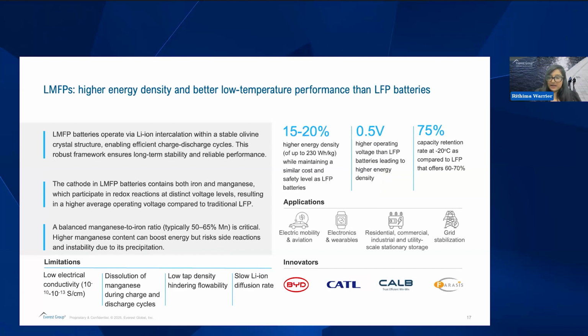Now, moving on to LMFP batteries. LMFP batteries are nothing but an upgrade of LFP batteries, and let me explain how. It's just that one letter M, which is manganese. So it is lithium manganese iron phosphate, which means that instead of entirely iron, it is able to incorporate manganese as well. And what this addition of manganese does is it allows the battery to work at distinct voltage levels. Because of the iron and manganese, there are distinct voltage levels, which overall results in a higher operating voltage of the batteries. So you can see it's almost 0.5 volts higher than the conventional LFP batteries.